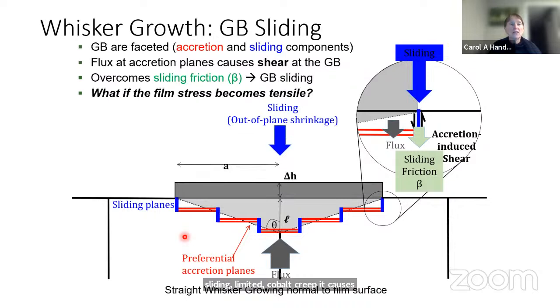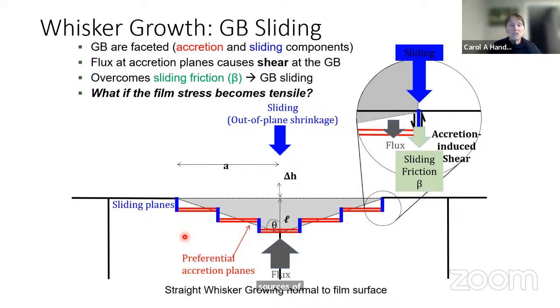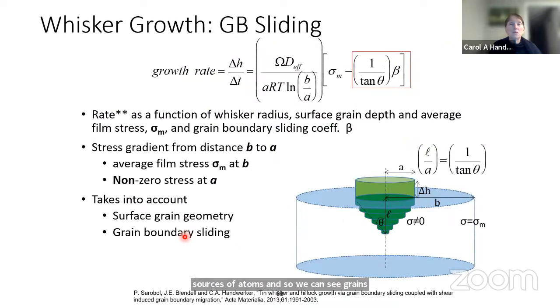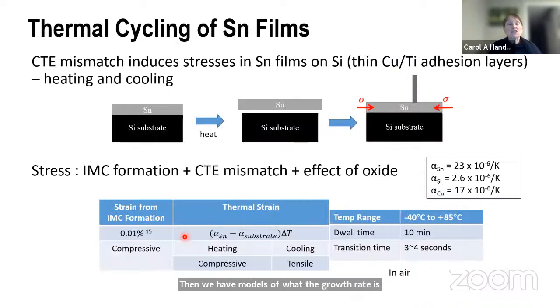And so if the film becomes tensile, what we have is actually these grains can become sources of atoms. And so we can see grains growing and shrinking. And I just recommend you going to the paper, and we have models of what the growth rate is as a function of these parameters. So I'm going to show you a few experiments where we have additional phenomena that are happening.